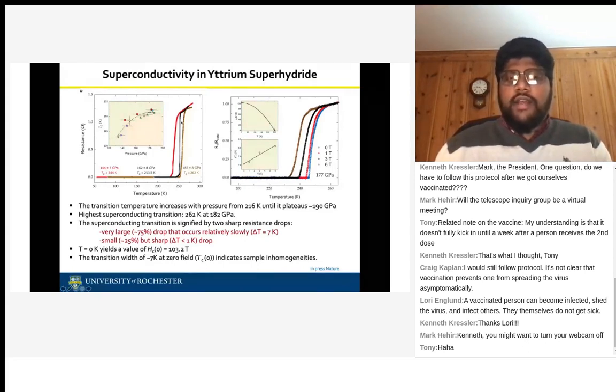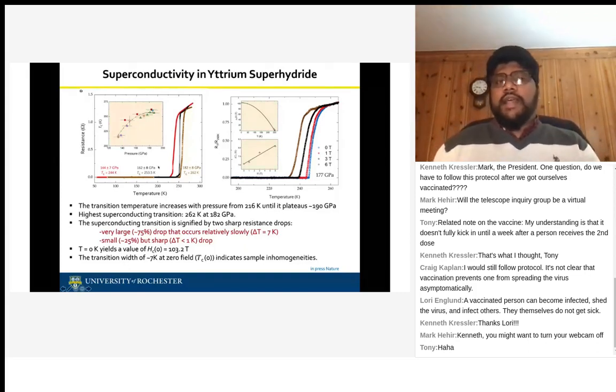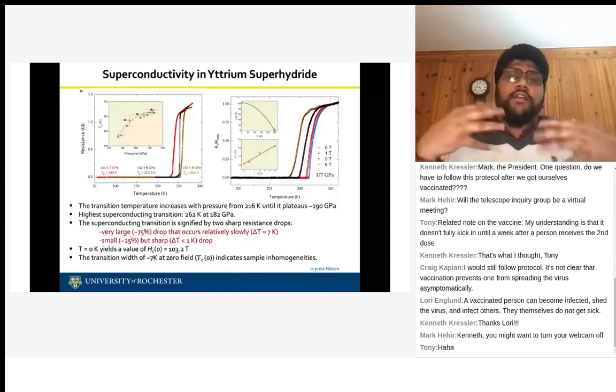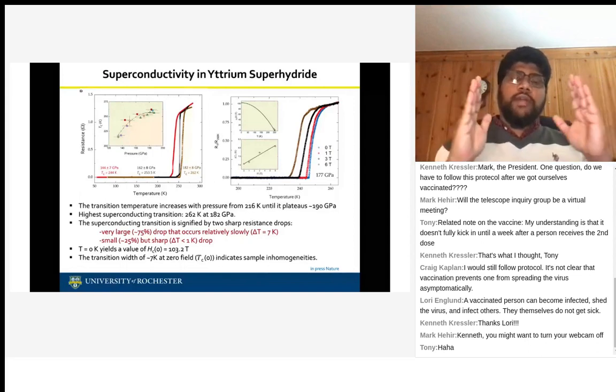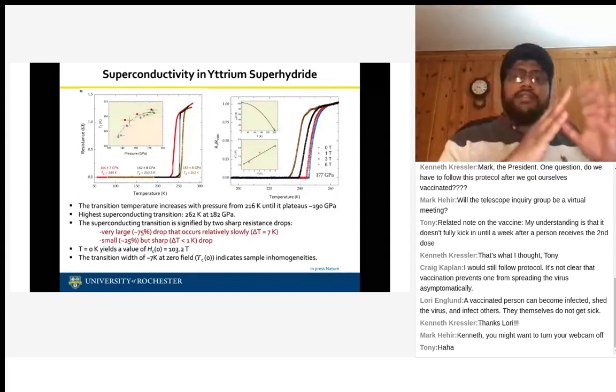That's like minus 12 degrees Fahrenheit. Actually, on a winter day, it's almost room temperature in Rochester. So you have a new material with room temperature superconducting properties. Of course, there are other ways that you can verify the superconducting transition. One way is to apply a magnetic field. Generally, magnetic fields are sort of the enemy of superconductivity. They can destroy the superconductivity. So depending on the strength of your magnetic field, your superconducting transition temperature can be suppressed.